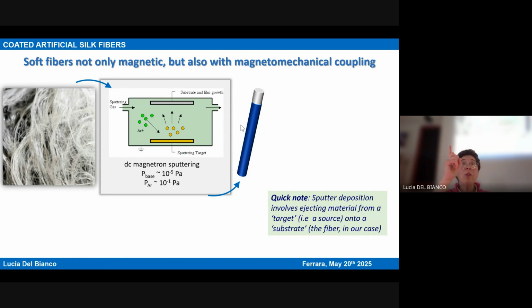I mean, really around one fiber, one piece of fiber of some centimeters, but not around the bundle, just one, which is not at all easy. It's something crazy, actually. But that was the idea, and we tried to do that by using a vapor deposition technique, which is sputter deposition. We have here the apparatus in our lab. It's the leading technique to coat materials or to grow thin films. It's very used also at industrial level, especially in the field of electronics, for instance. Substantially, it means that you have a target which is bombarded by accelerated ions, and therefore some atoms are ejected and move towards a substrate where they form a film.